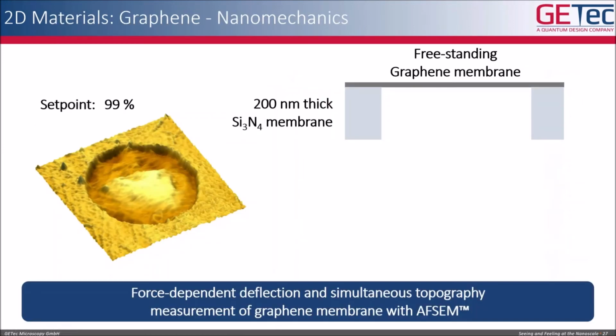What we did is perform an experiment in dynamic or tapping mode where we worked with a set point of 99%. For those familiar with AFM, that means we only have an amplitude damping of the cantilever oscillation of 1% needed to get into feedback with the surface. If you're used to working in AFM with air, you need to penetrate the water layer present on every surface under ambient conditions.